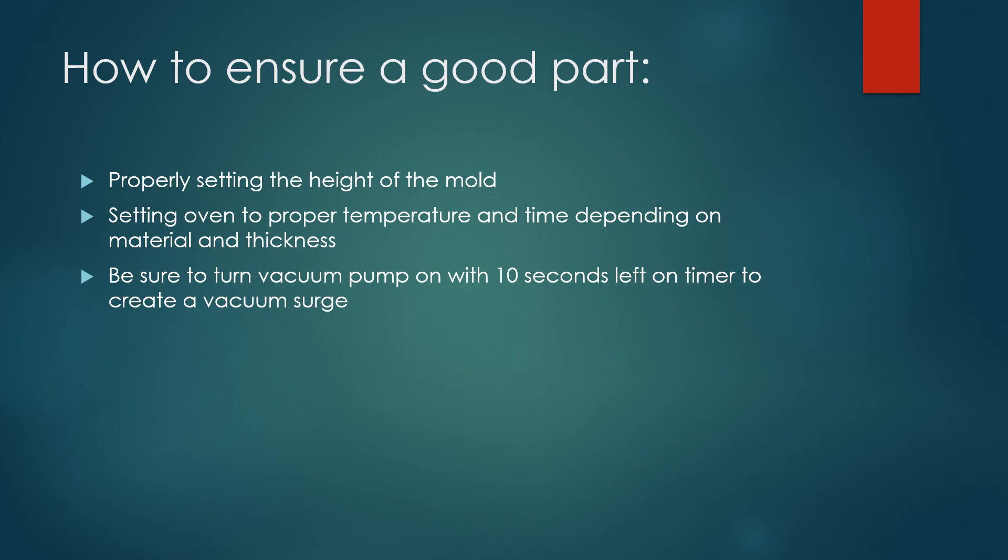And then the last thing is, be sure to turn on the vacuum with 10 seconds left on the timer to create a vacuum surge. That's just very important to get your part to take the shape of the mold.